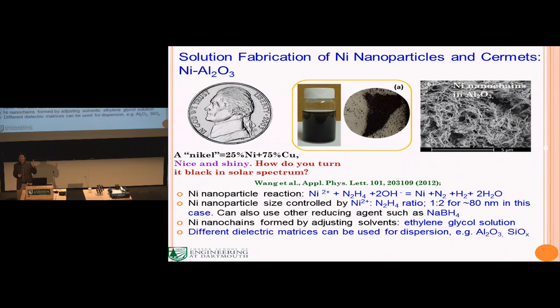Yes. Actually, we discussed that in the paper, but I later removed that slide because I thought it was probably too much to discuss. If you have the polarization of light along the nanochain, depending on how many particles you have in that chain, you can redshift the resonance, to the extent where the length is almost equivalent to the plasmon decay length of the electron oscillations. Beyond that length, because the plasmon can only propagate so far, it doesn't change the optical properties anymore. That's actually a good thing for fabrication, because our fabrication usually leads to nanochains of at least 10 nanoparticles. It's pretty long. So in that case, you can further redshift the interaction.